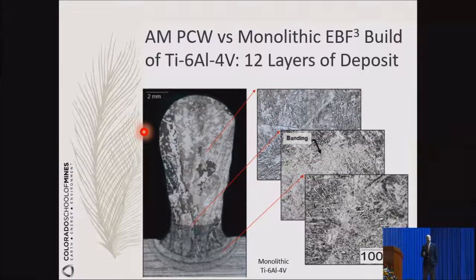Look at this first one here. This is made by a monolithic wire, which means a solid wire deposition using electron beam. So the electron beam hits the wire and then deposits onto your substrate. And here on this diagram, you have 12 layers building on top of each other. On the right-hand side, it's not that important, it shows you some of the metallurgical phenomena, such as banding and the microstructure. But the important thing is that you see the tremendous amount of epitaxial growth. So the grains will continue from layer to layer, from layer to layer, okay? But no visible defects.